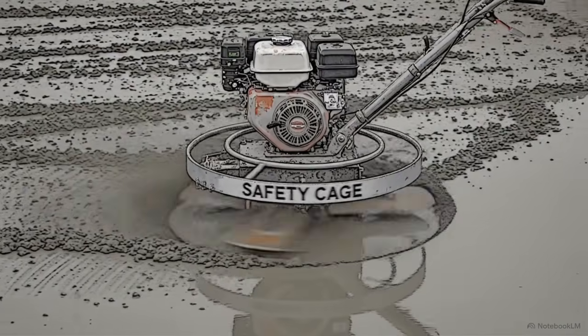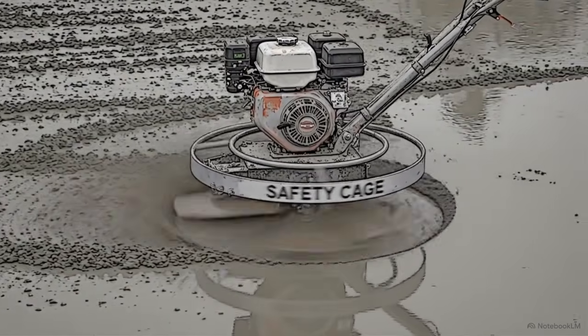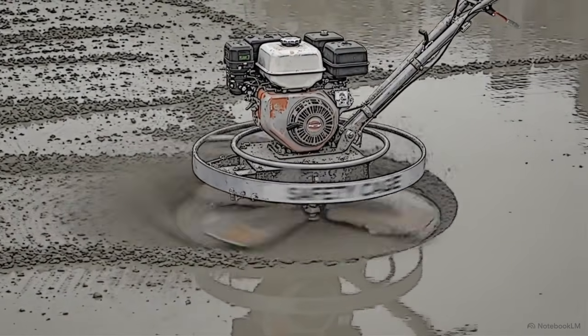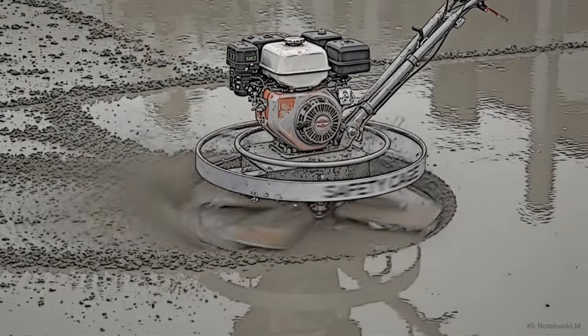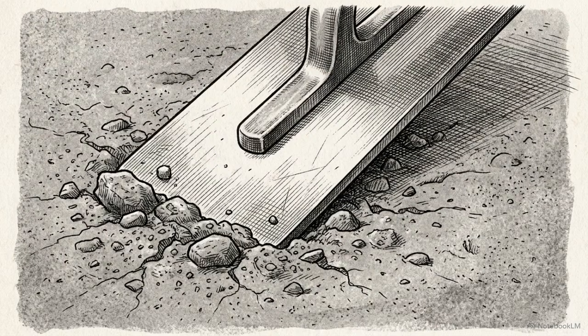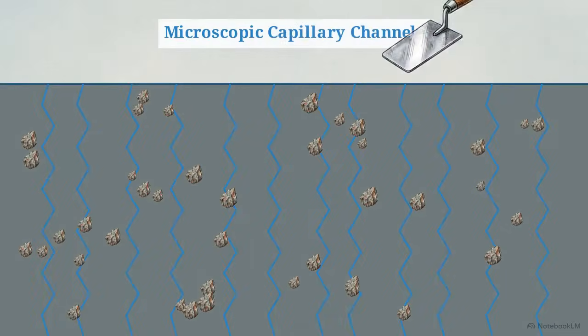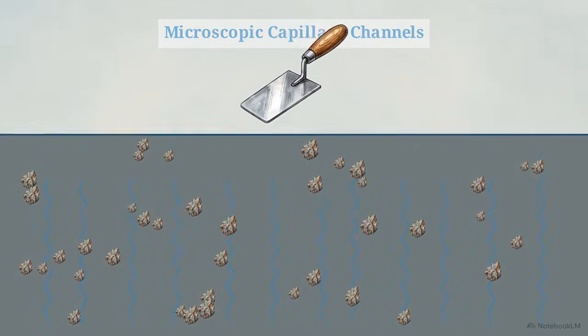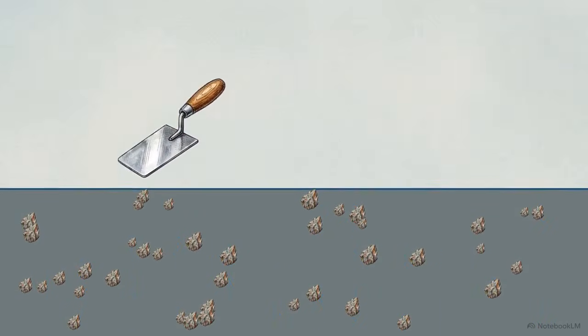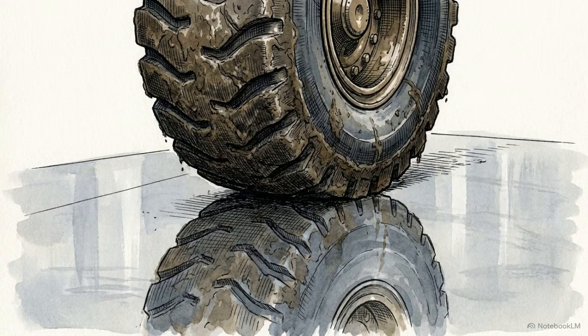A heavy power trowel spinning rapidly over the semi-dry concrete surface is then used to smooth the rough top layer. The mechanical function of this power floating step is to utilize raw kinetic energy and intense downward weight to compress the newly dehydrated top layer. This final downward compaction permanently closes the microscopic capillary channels that were left open by the escaping water. By sealing those vertical escape routes, power floating converts the dense internal matrix into an impenetrable surface shield, engineered to